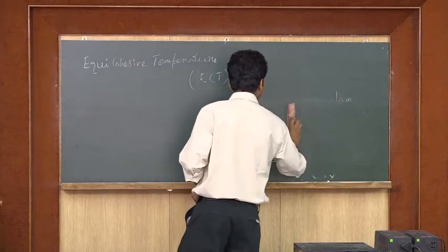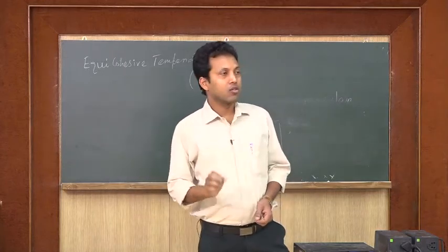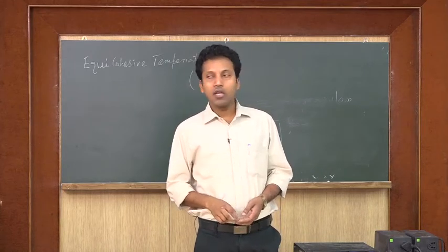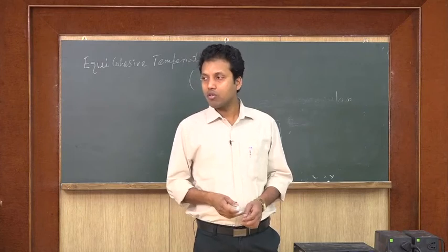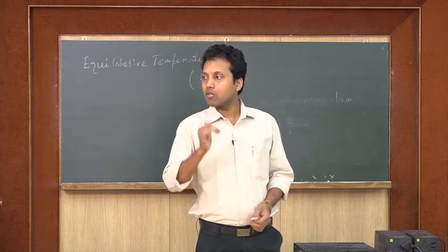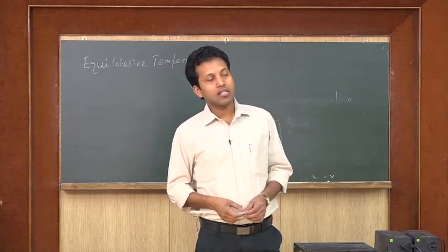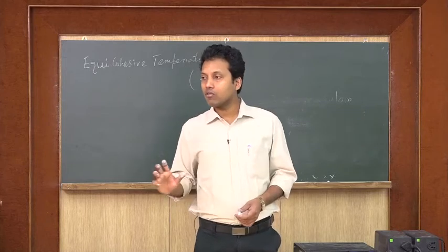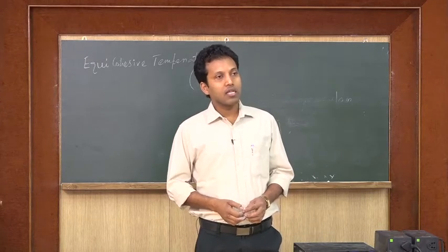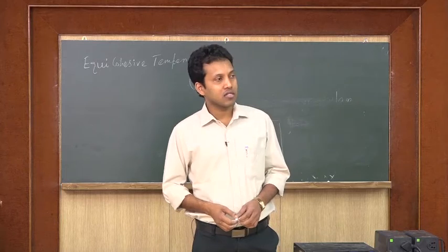Another interesting thing is, if I have a small grain size material, what does that mean? The number of grain boundaries is more, and if we are working at a temperature above the equicohesive temperature, all the grain boundaries are weak. As the grain boundaries are weak, cracks can grow through them. So, above equicohesive temperature, if a material is fine grained, then its strength is less.